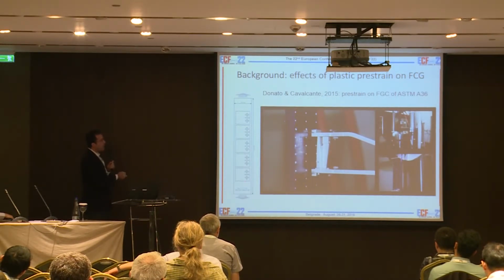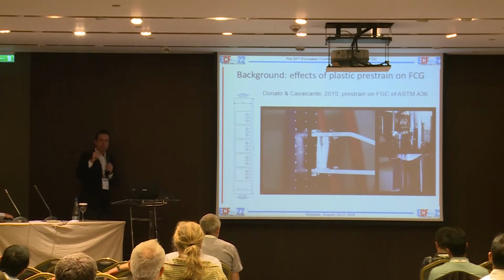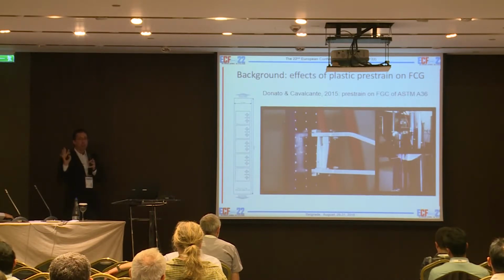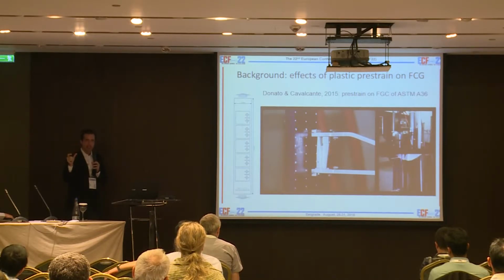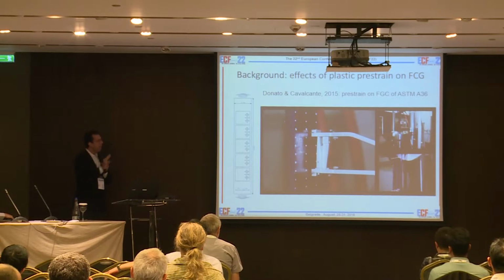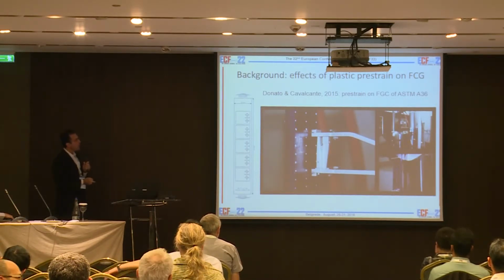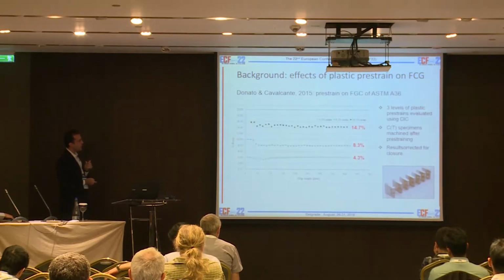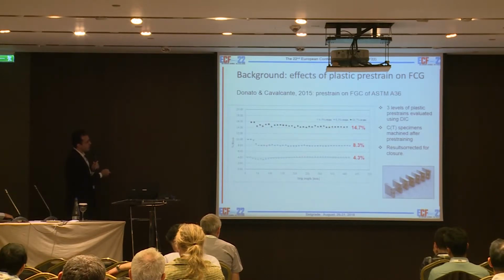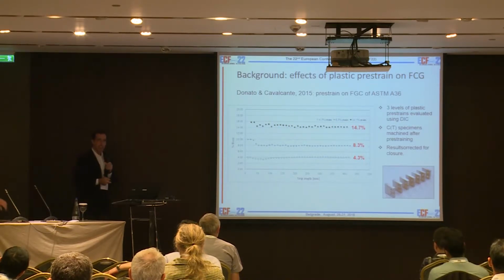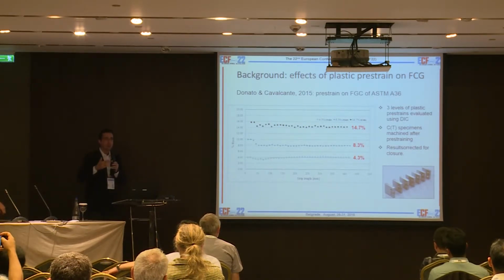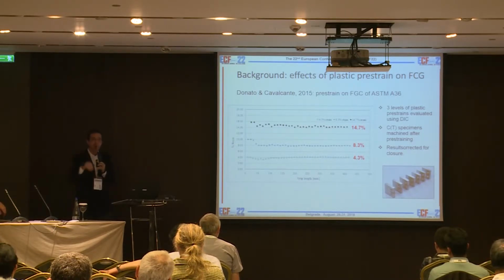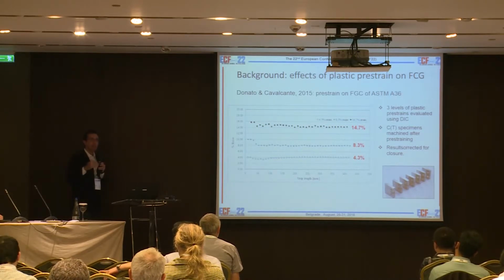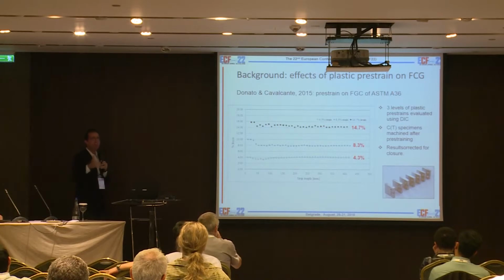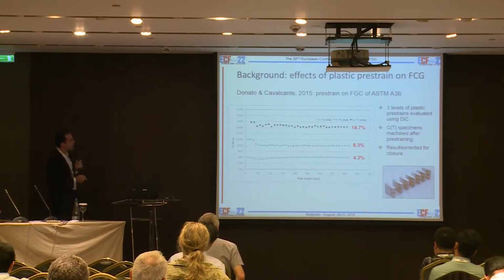We developed some strips. We, first of all, pre-strained the strips to have a uniform strain field. Parallel to that, we also pre-strained CT specimens ready to test, so we had the two conditions. Here I'm presenting the results of the pre-strained strips. We used DIC and also another optical technique to have the reference, and here you can see along the strips the distribution of plastic pre-straining: 4.2, 8.3, and 14.7%. These were values that were interesting for us in terms of the range that UOE and calendering imposed in our applications. It cannot be extended to other values, but if we need, we can test additional values because we have extra material in our lab.